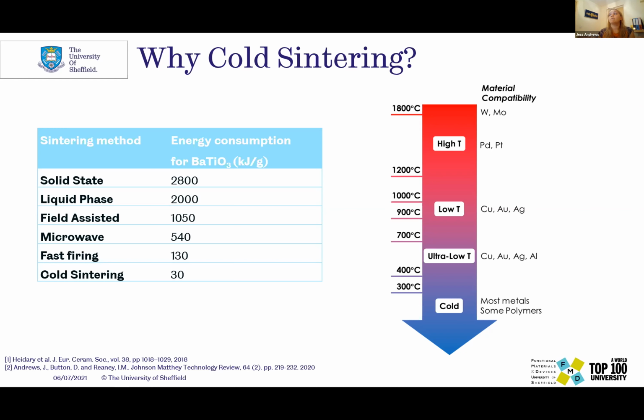Another major benefit is that if we reduce our processing temperatures, then we can improve the different materials that you can add into your components. So you can co-sinter with a broader range of metals with lower melting temperatures and lower glass transition temperatures, but also at 200 degrees and below, you're looking at getting lots of polymers involved, and so you can make some really exciting structures.